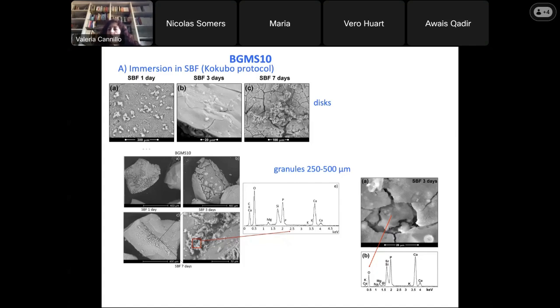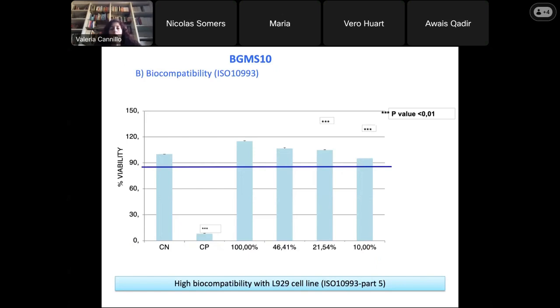And in the picture, you can see the BGMS-10 granules after immersion in SBF for increasing times. Just after 1 day, the surface is characterized by several cracks. And after 7 days, it is possible to observe the formation of white globular precipitates, which are typical for hydroxyapatite. The results of EDS analysis performed on the precipitate found a calcium to phosphorus ratio of about 1.67, which is the stoichiometric value of hydroxyapatite, thus confirming the bioactivity of the BGMS-10. So, coming to the biocompatibility, according to ISO norm, the biocompatibility was tested with the L929.